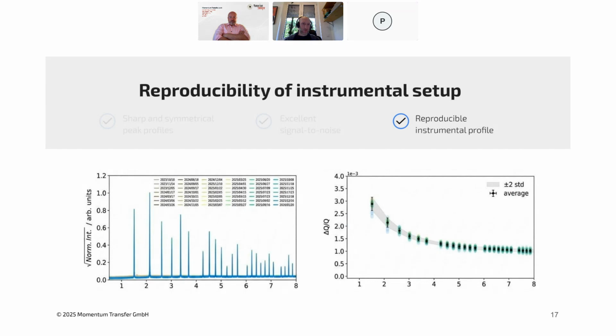And also we have a very reproducible instrumental profile. So one of the tricky things working with these facilities typically is done through general user programs, where people apply or buy beam time to come. But because these beamline stations are very flexible to do lots of different kinds of measurements, oftentimes you get the whole system in a slightly different state every time you use it. So sometimes you use slightly different wavelengths. Sometimes the detector needs to be in a slightly different position. Sometimes different devices have been changed in between. So we are generally dealing with hardware upgrades, but we try to mitigate that by making proper corrections in the data processing to account and normalize for all of those.